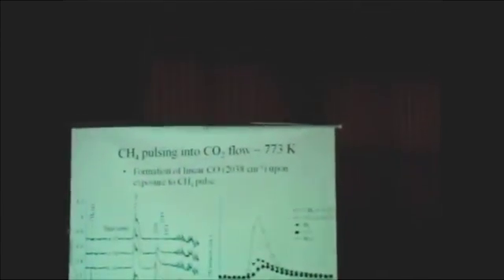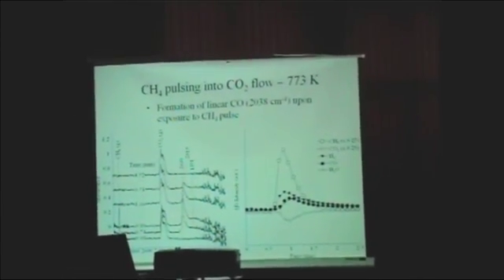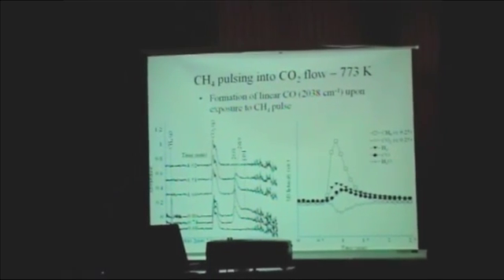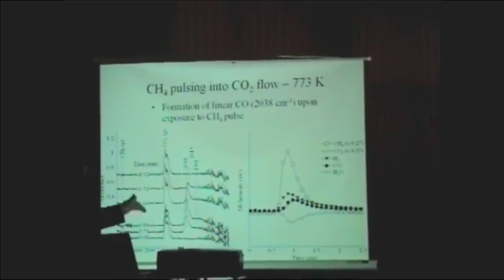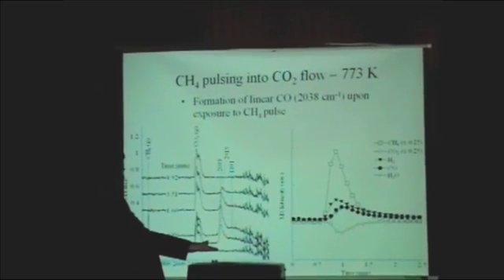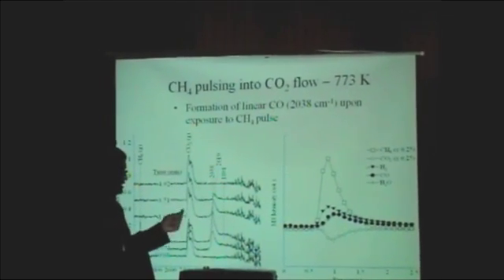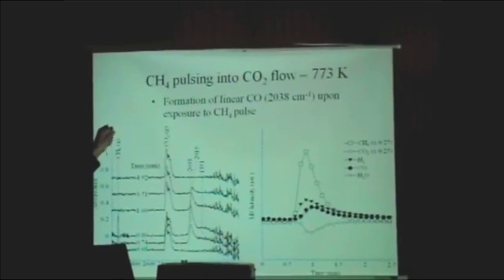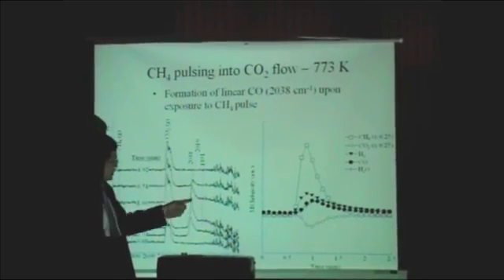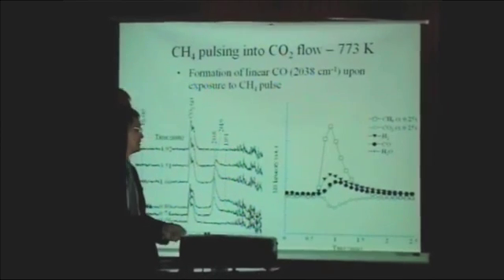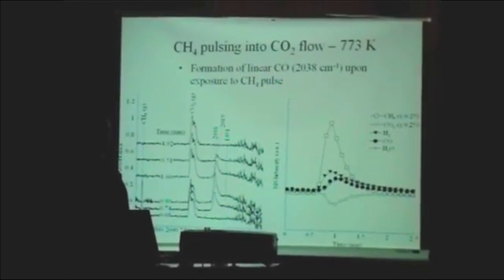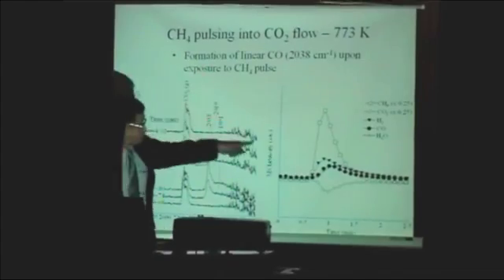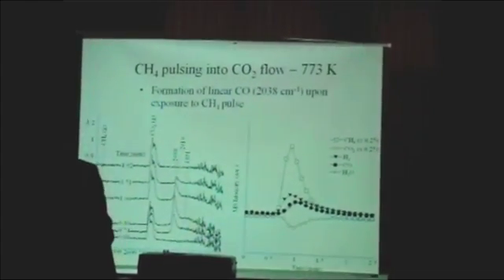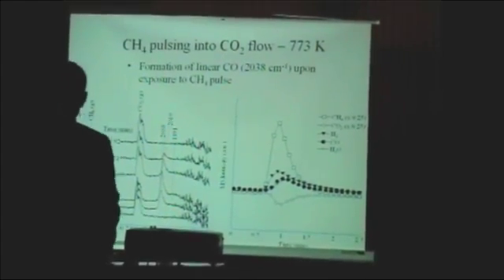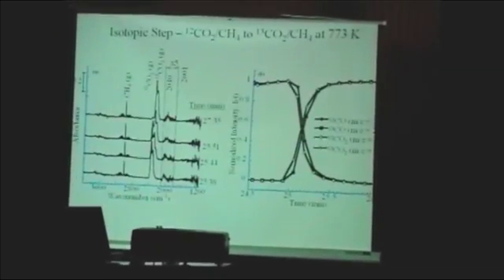So from here, we can see methane coming in and promoting the formation of CO. We don't see any adsorbed CO2 on the surface, but once methane comes in, the oxygen on the CO2 can be easily pulled out to generate CO, which is immediately formed on the catalyst surface. And the hydrogen comes from the methane, promoting the formation of hydrogen. So we can pulse the CO2 into methane and pulse methane into CO2 using this technique to determine which one is forming first.